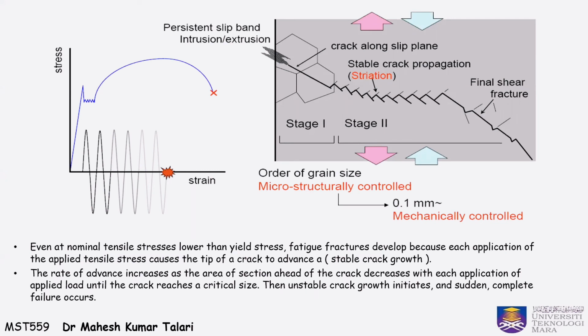As we can see in the figure here, it shows the steps involved in crack propagation. In the first stage, the initial slow propagation is involved, and we can see that the crack propagation occurs along the crystal plane with a high resolved shear stress. It involves just a few grains, and it has a flat fracture surface. When it proceeds to stage 2, faster propagation perpendicular to the applied stress occurs. The crack grows by repetitive blunting and sharpening at the crack tip, producing a rough surface. And finally, the crack eventually reaches a critical dimension and will propagate very rapidly.